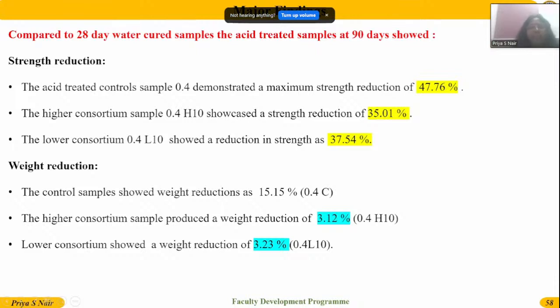Compared to the 28-day water cured sample, the acid treated samples at 90 days showed that the higher consortium had a 35.01% strength reduction, and the weight reduction was only 3.12% compared to the others.